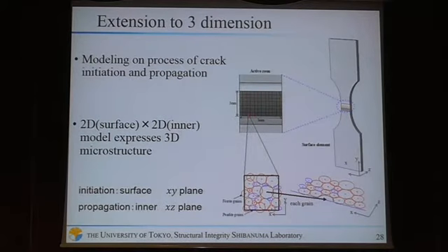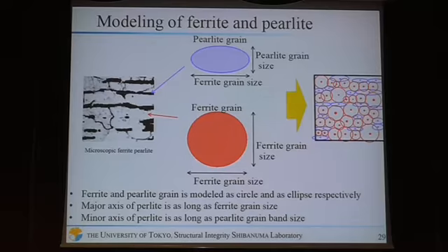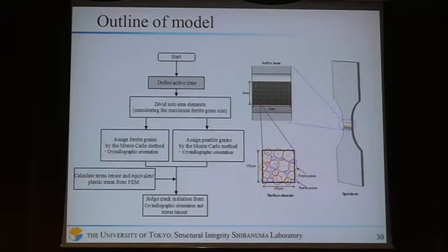So we did an extension to 3 dimensions. This study models the surface of the specimen as a 2D surface and the inner part of the specimen as 2D. In modeling of ferrite-pearlite grains, this model regards a ferrite grain as a circle and a pearlite grain as an ellipse based on a preceding study. This is the outline of this model.